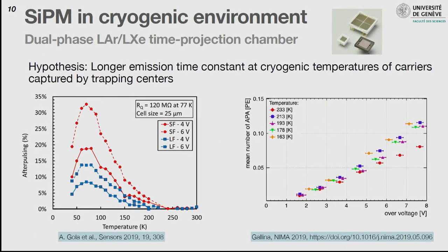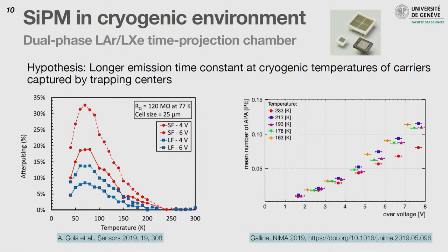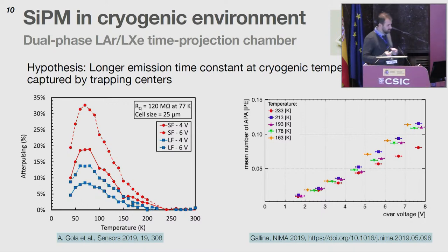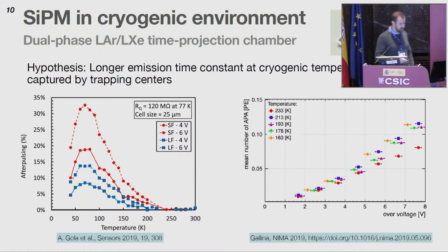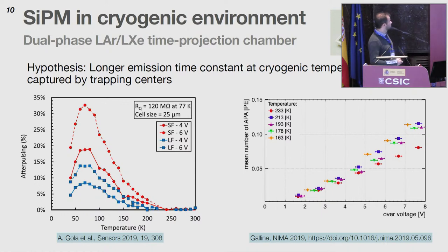Photo detection efficiency is not yet at the level of PMTs, which can reach 30% or more. Hamamatsu reaches about 20% and FBK about 15%. After-pulsing increases a lot when you go down in temperature. The hypothesis is that at room temperature carriers recombine faster, so the cell recharges before the after-pulse occurs — hence nearly zero after-pulses at room temperature. This competes with polysilicon quenching resistors, which increase at low temperature, causing longer recovery time.